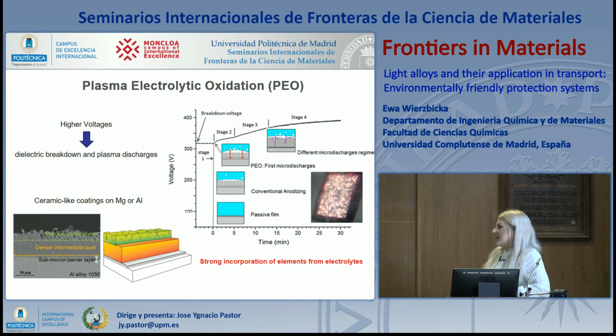Because of that, the plasma has very high temperature and pressure, and it can go through the discharge channel and form the layer on the surface. The coating obtained this way has 3 layers. The top layer is quite porous, the intermediate layer has a quite dense structure, and there is also a barrier layer without any pores. It is also worth mentioning that these techniques allow strong incorporation of elements from the electrolyte.